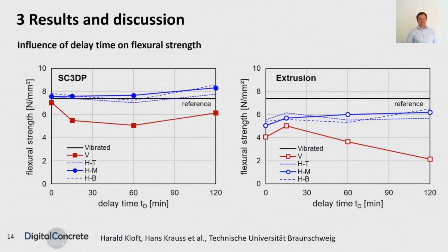if we take a look at the influence of delay time on flexural strength, then we can see some clear effects of the process itself as well as of the delay time. So first, if we take a look at the blue curves, then we can see no clear effect of delay time in both cases. You can see a horizontal development of the curves independently whether it was the main interface here, HM, or the standard interface, HT and HB. This seems to have no clear effect if the main interface is allocated parallel to the long axis.